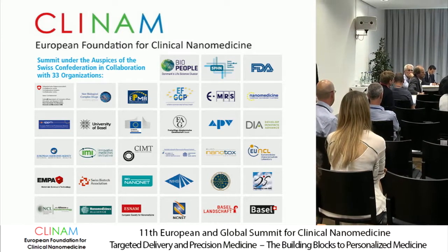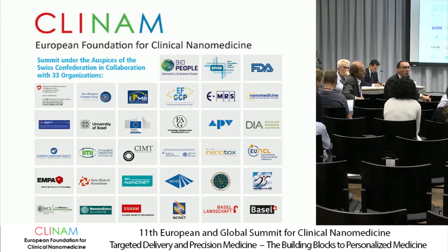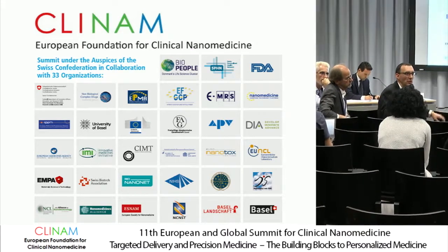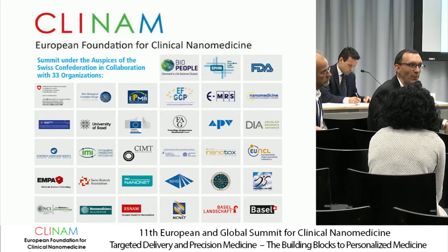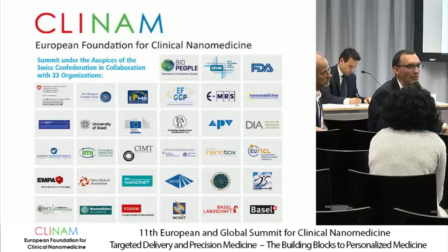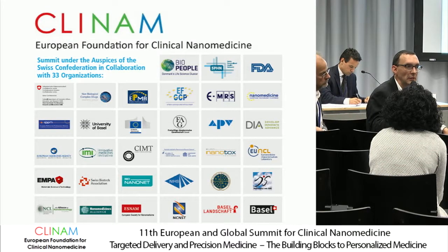To pick up the discussion about complex samples, I think in particle analysis it's important to gain a priori knowledge of the sample. In analytical chemistry, you have a question like, I'm looking for gold, so I look for gold. In particles, you look for size and concentration, and it's really dependent on the technique and how the data is generated. In DLS or nanoparticle tracking, it's light scattering, which traces back to refractive index. So if you can feed a little bit of refractive index back to it, this helps.